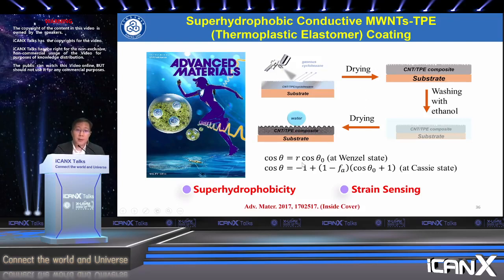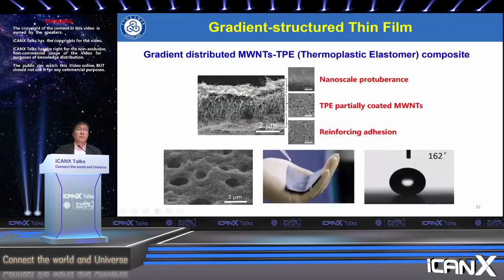Composite material, with a very rough surface, increases the surface roughness and also the air friction, so it gives the property of super hydrophobicity. And from the cross section of the image, you can see that there's a gradient distribution of the carbon nanotubes and also the thermoplastic elastomer composite.